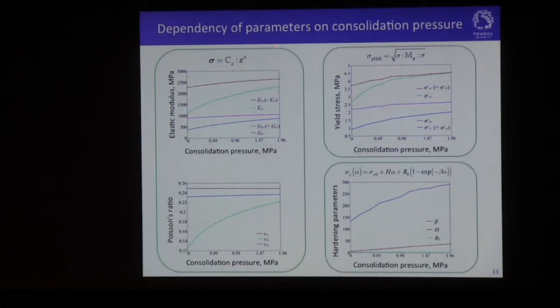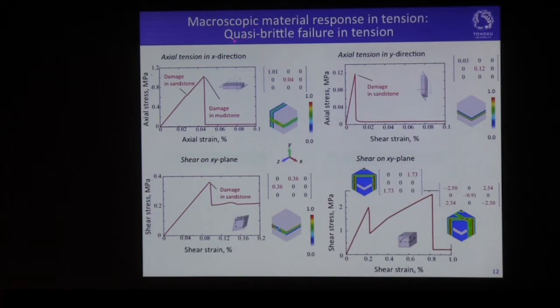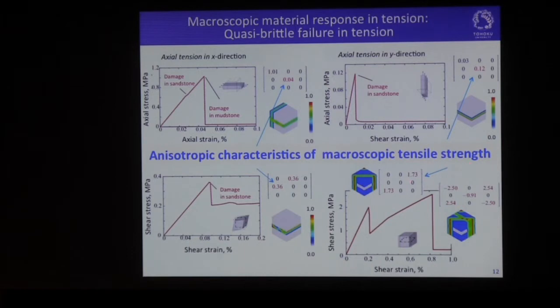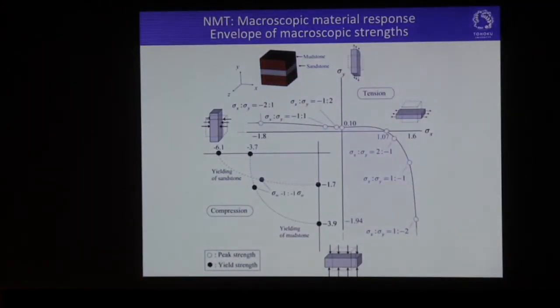Then we also have to evaluate the dependency of the material parameters on the consolidation pressure. So as you can see here, these are the functional representations of the dependencies. Now, this is the macroscopic material response in tension as a result of the numerical material testing on the unit cell that exhibits quasi-brittle failure in tension. Okay, as you can see, depending on the macroscopic loading patterns, we have an anisotropic characteristic in the macroscopic tensile strength, like this. So we can put all these macroscale material responses into this kind of envelope of macroscopic strength. Here shows the tensile region of the material response, and this is the compressed region of this macroscopic material response. Then we can utilize this kind of envelope for the macroscopic strength assessment.